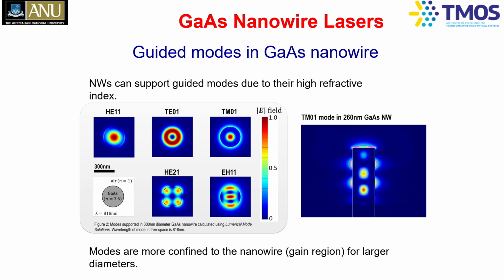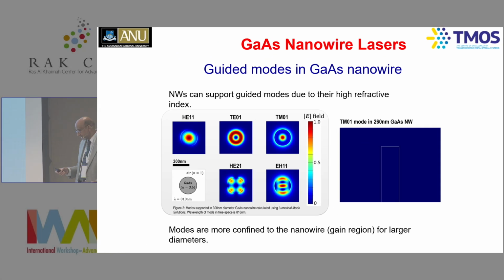Drew's simulations have shown that if you use 50 or 30 nanometer nanowires, which is what we initially started with, they're not able to really propagate the light, and also they start burning before any lasing starts taking place. So that's why we had to go for larger diameter nanowires.